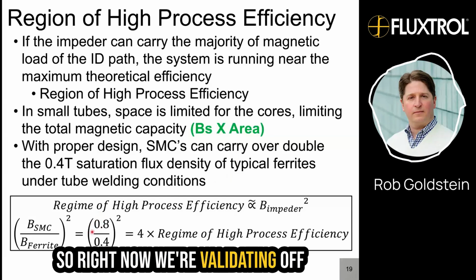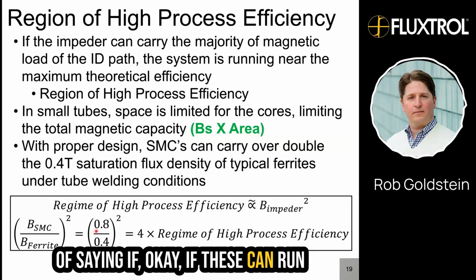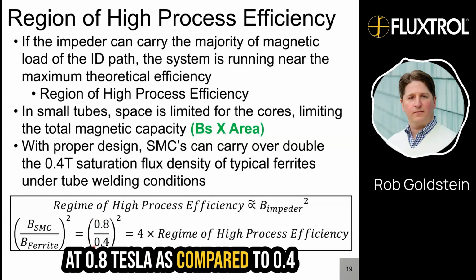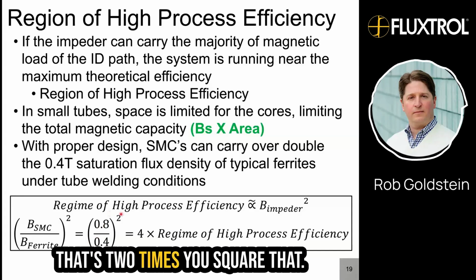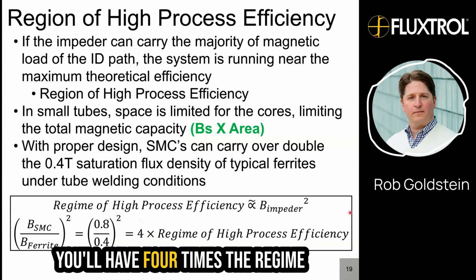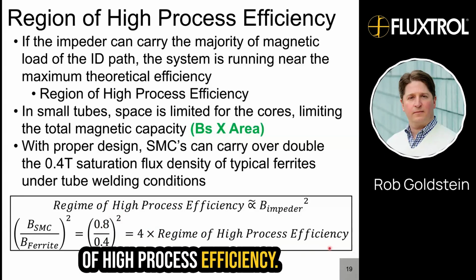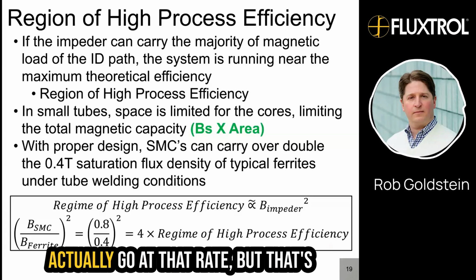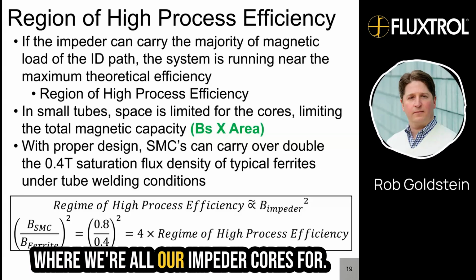So right now we're validating off of saying if these can run at 0.8 Tesla as compared to 0.4, that's 2 times. You square that, you'll have 4 times the regime of high process efficiency. We still haven't found one that can actually go at that rate, but that's what we're designing all our impeder cores for.